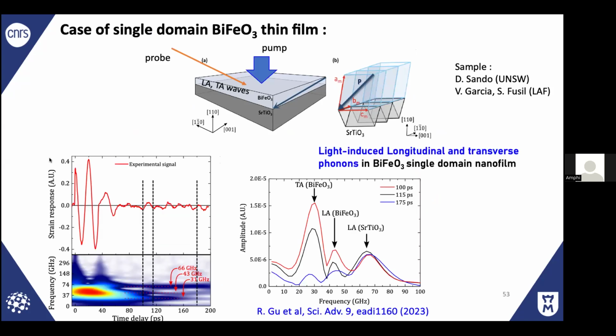And we did the same thing for thin films. What you saw before was for bulk bismuth iron oxide. This is the same thing for thin films, samples grown by colleagues. This is 150 nanometers. You shine light on such a thin film, and because of the symmetry breaking due to ferroelectric polarization, if you make a Fourier transform, you can get longitudinal and transverse. What was very important in the community of coherent acoustic phenomena is also to know exactly what the amplitude is, what the efficiency of the light energy conversion into mechanical energy is.